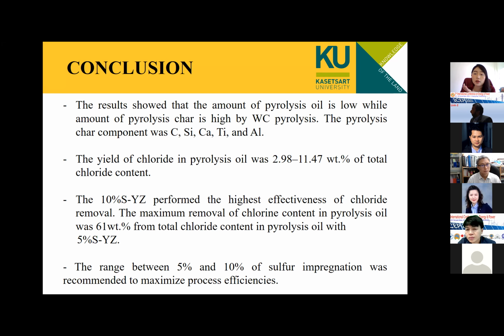In conclusion, the results show that the amount of pyrolysis oil is low while the amount of pyrolysis char is high by WC pyrolysis. The pyrolysis char components were carbon, silicon, calcium, titanium, and aluminum ions. The yield of chloride in pyrolysis oil was 2.98 to 11.47% by weight of total chloride content. The 10% sulfur rate gave the highest effectiveness of chloride removal, with a maximum removal of 61% by weight of the total chloride content in the pyrolysis oil with 5% sulfur. A sulfur impregnation between 5 and 10 was recommended for maximum process efficiency.